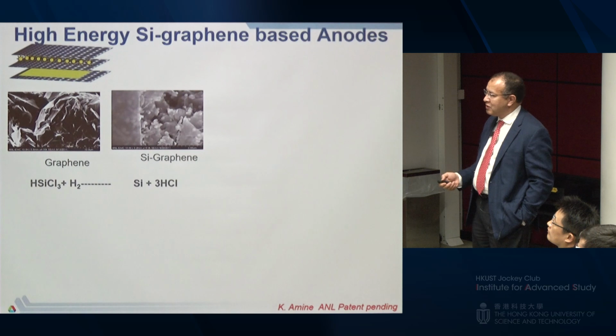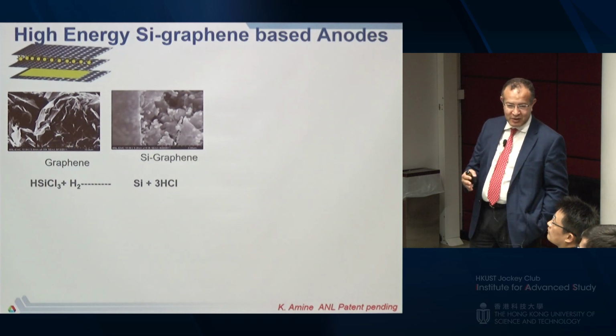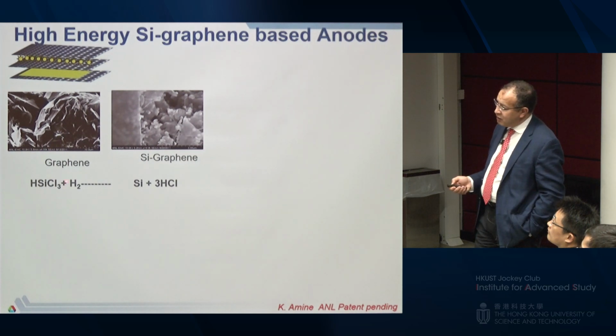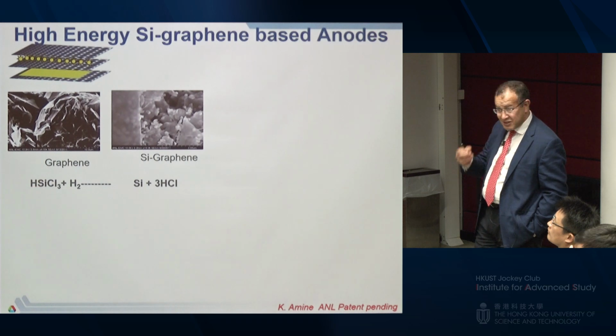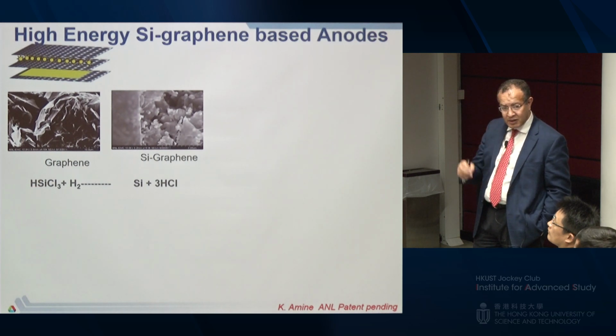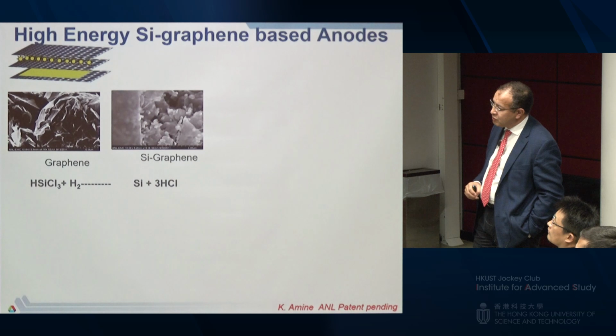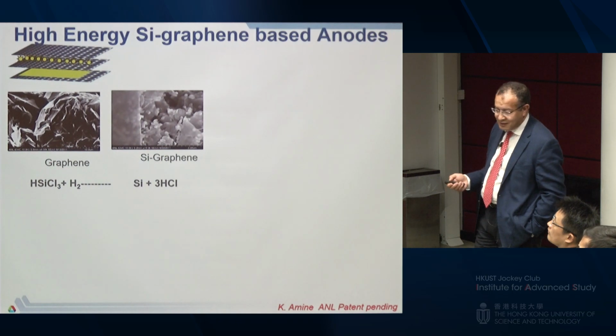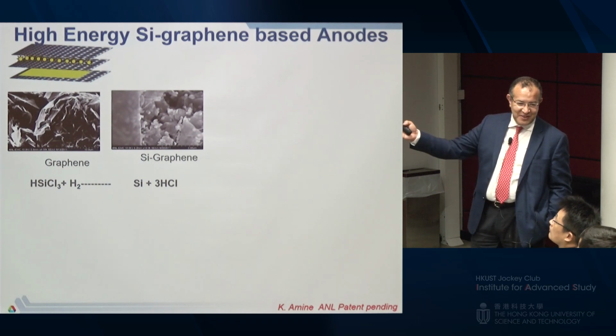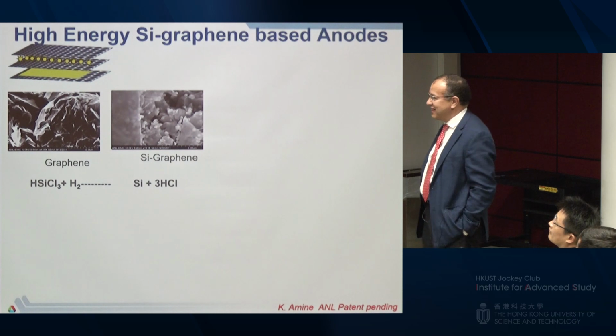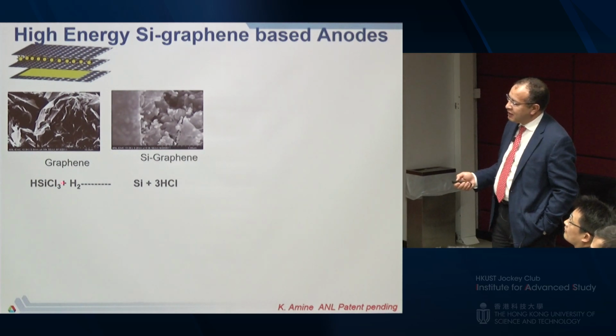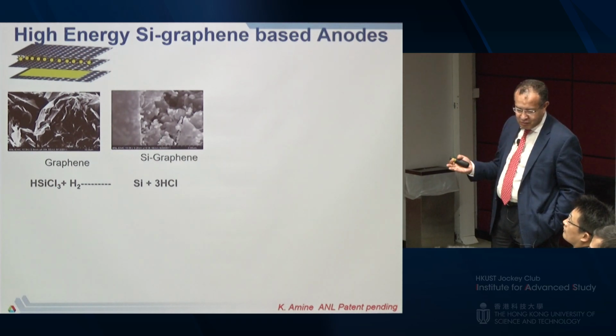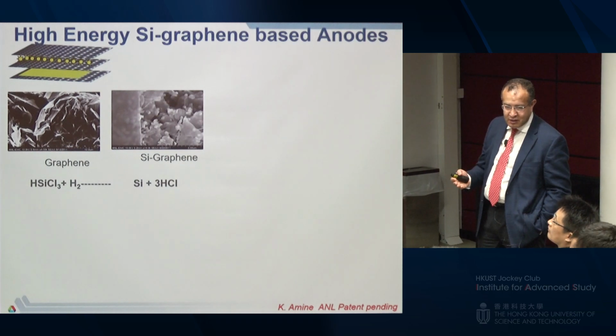So basically the byproduct is huge, about 80% is byproduct waste. And they struggle to get rid of it because this is a dangerous gas. So you really have to have very special tools to take care of it. So in our case, we thought, okay, we can use it as a byproduct. The silicon fab will give it to you for free because they will reduce the cost of getting rid of it. And then basically use graphene by exfoliating graphite using acid, very disordered.